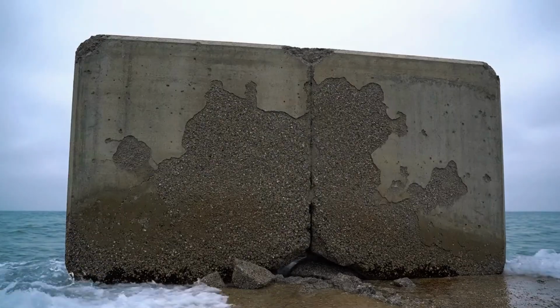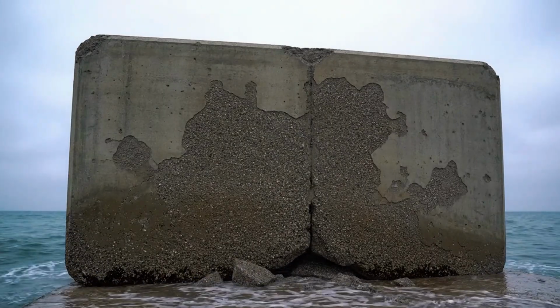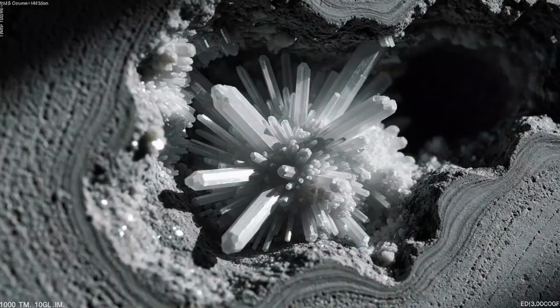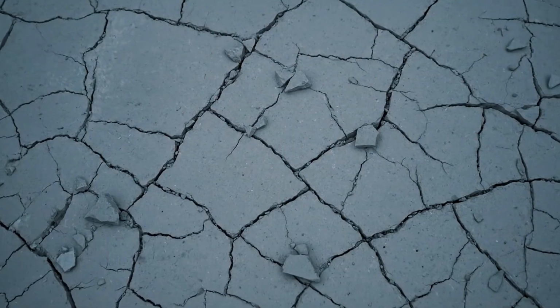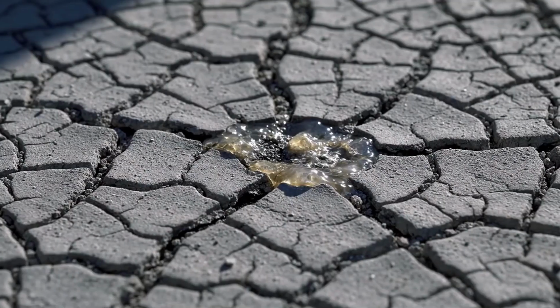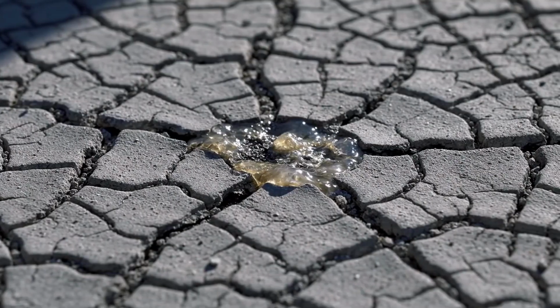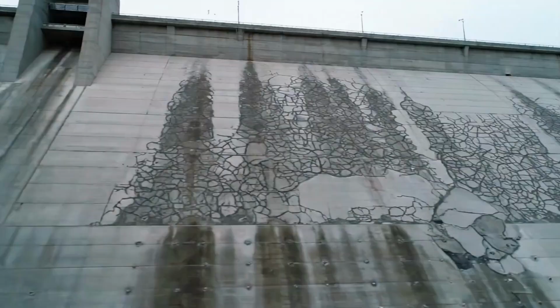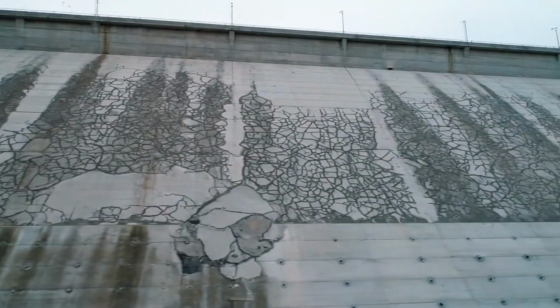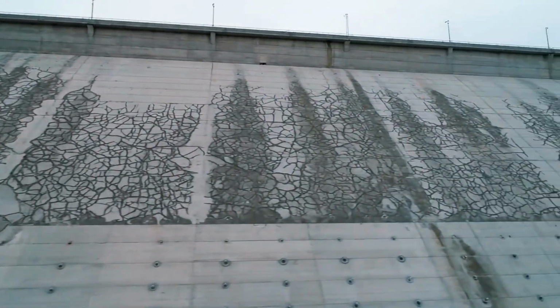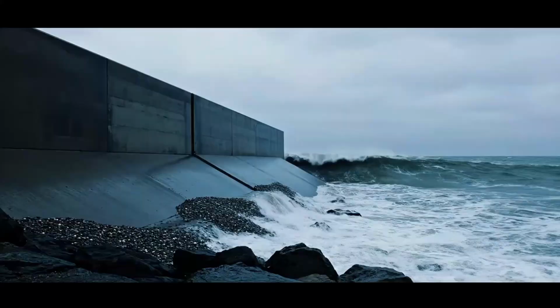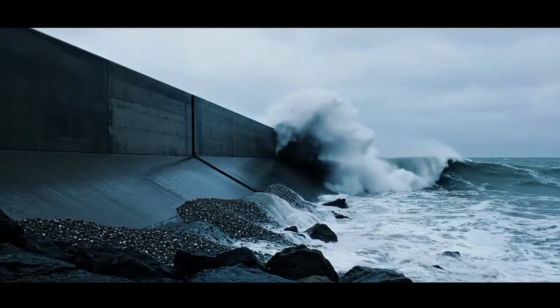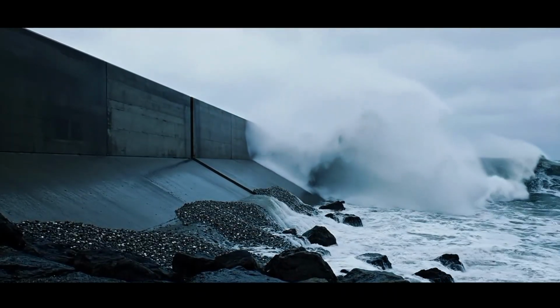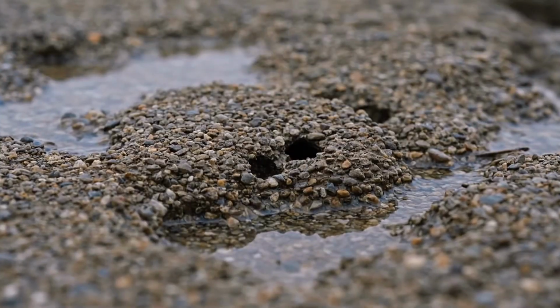Second, sulfate attack. Seawater also contains sulfates, which react with compounds in Portland cement to form expansive crystals. These crystals grow inside the concrete matrix, creating internal pressure that causes spalling, surface chunks breaking off. Third, alkali-silica reaction. If the aggregate contains certain types of silica, it can react with the alkaline pore solution in the cement, forming a gel that absorbs water and expands, cracking the concrete. And fourth, simple erosion. Waves, tides, freeze-thaw cycles, and mechanical abrasion gradually wear away the surface.